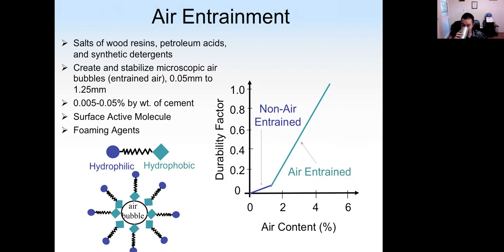So air entraining agent is a surface active molecule. Look at the molecule structure. It has a hydrophilic end, which means it likes water. The other end is hydrophobic, which means it hates water. Because of the nature of this molecule, they will form air bubbles, and these air bubbles can also be stabilized inside cement paste.